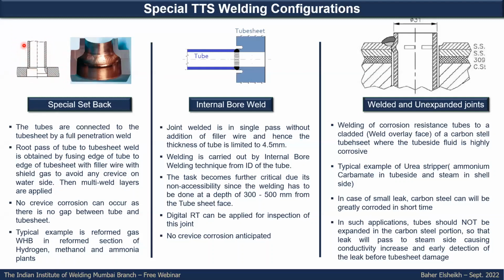And in the shell side, there is boiler feed water. Even with minor contamination of the salts in the boiler feed water, you might have the crevice corrosion here of much higher risk. And this internal bore welding, where the tube actually is not inserted into the tube sheet, but it is butt welded to the back side of the tube sheet. This application is called internal bore weld.